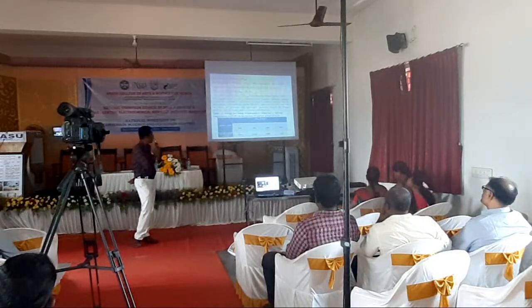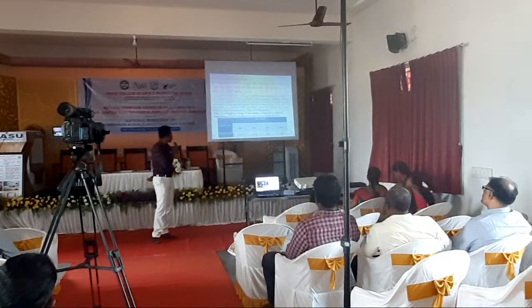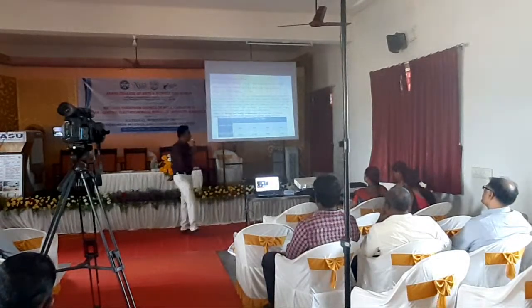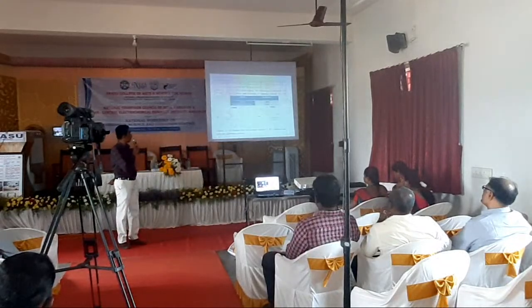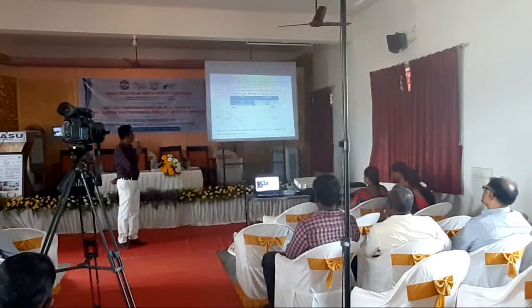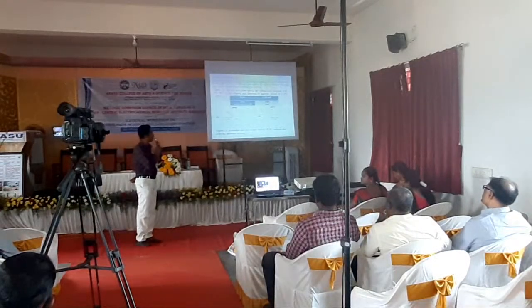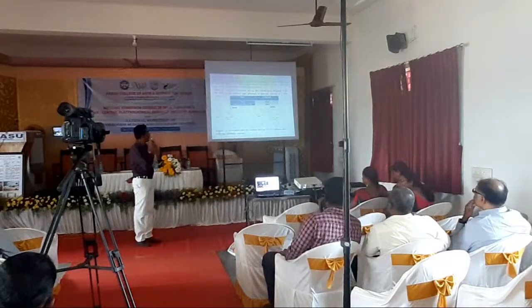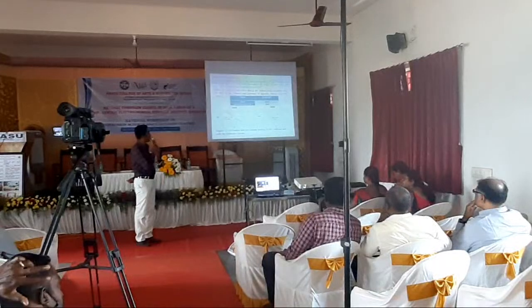Free energy of adsorption: the blank solution at 303 Kelvin is 12.106, and the last one at 333 Kelvin is 13.503. So the inhibition efficiency also increases. Next. Energy of activation: for the blank solution it is 26.20, and with the aqueous extract of Carissa carandas plant leaves inhibitor added it is 53.30. The energy of activation increases.